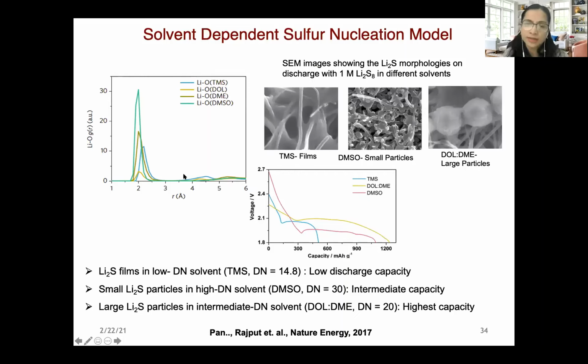And we found that as we are increasing the donor number of the solvent, we are increasing the lithium and solvent interaction. And that was a very monotonic trend. So the lowest donor number is for TMS solvent, the highest is for DMSO, and we observed a linear trend here. Okay. And we looked at the effect of this solvation structure on the nucleation of lithium polysulfide species, where